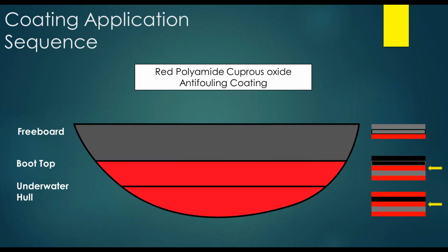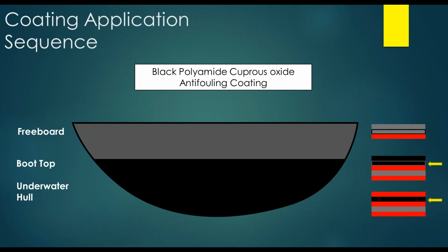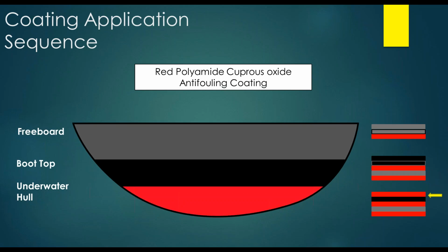A red anti-fouling coating composed of a polyamide and cuprous oxide was applied to both the underwater hull and the boot top. This was followed by a black anti-fouling coating on the boot top and the underwater hull. A red anti-fouling coating was applied only in the underwater hull to differentiate the boot top from the underwater hull, and a second layer of the black anti-fouling coating was applied in the boot top. Finally, a polysiloxane coating was applied to the freeboard to give it the UV stability.